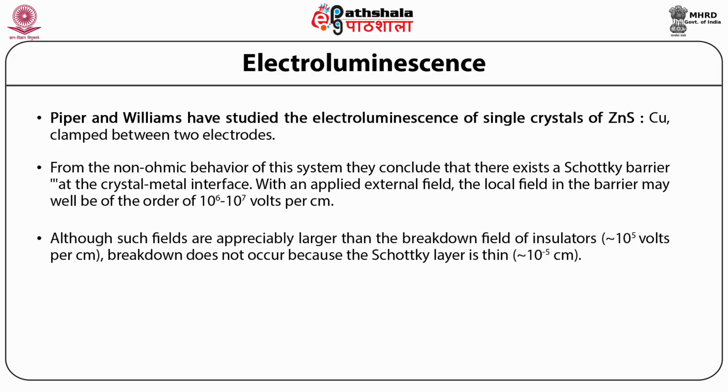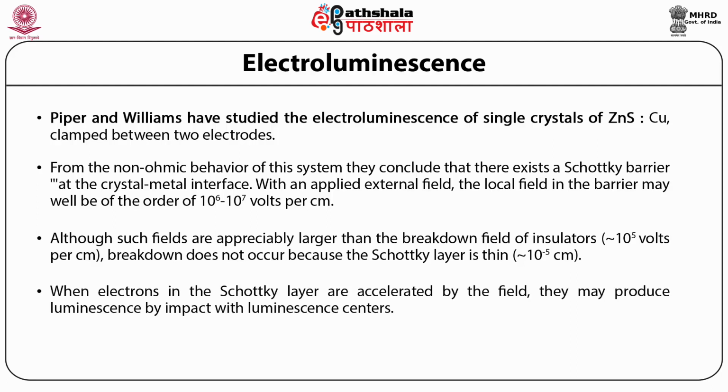Although such fields are appreciably larger than the breakdown field of insulators, of the order of 10^5 volts per centimeter, breakdown does not occur because the Schottky layer is thin, of the order of 10^-5 centimeter. When electrons in the Schottky layer are accelerated by the field, they may produce luminescence by impact with luminescence centers.